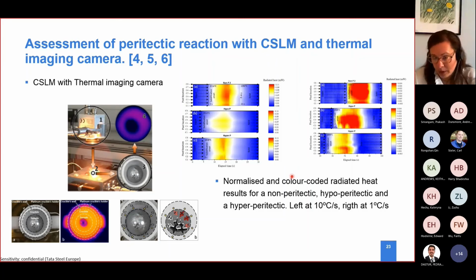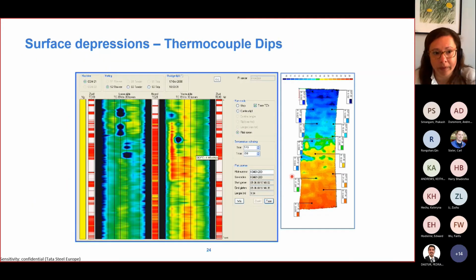Why is it so important to understand that? Why is it so important, particularly why did we focus on peritectic grades? Because while we cast, peritectic grades are very prone to shrinkage. The shrinkage happens because of the phase transformation I explained just before, the peritectic one.